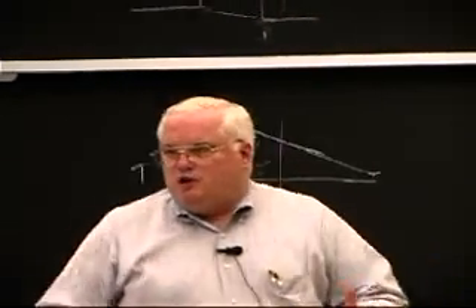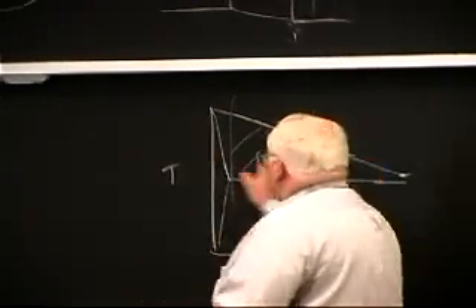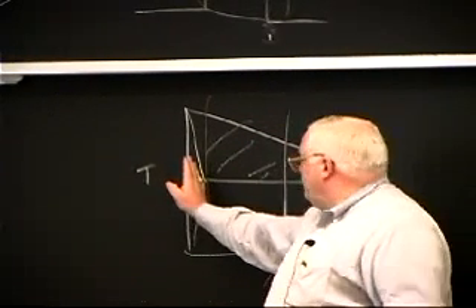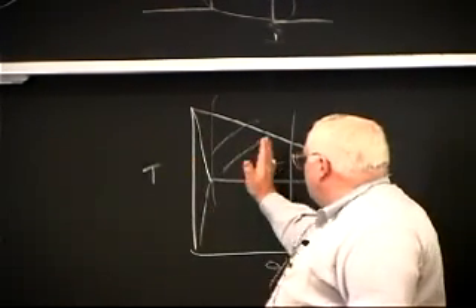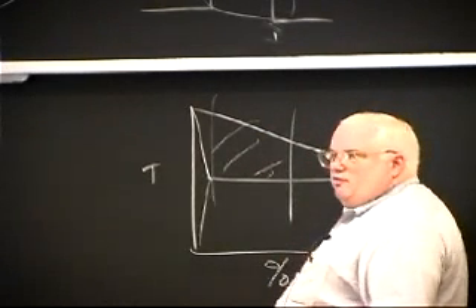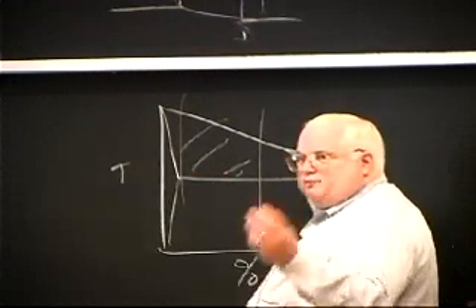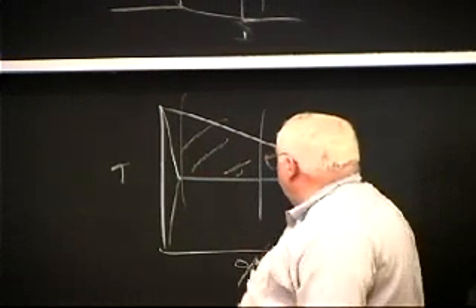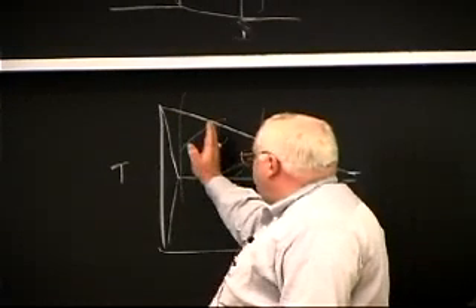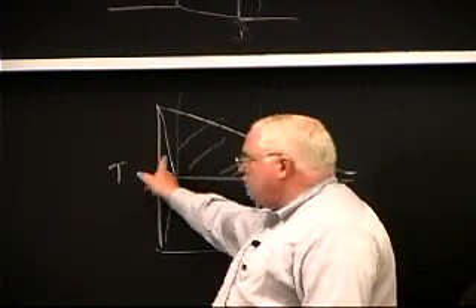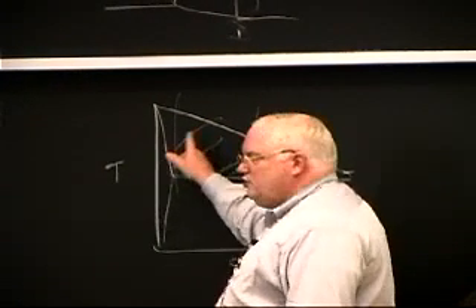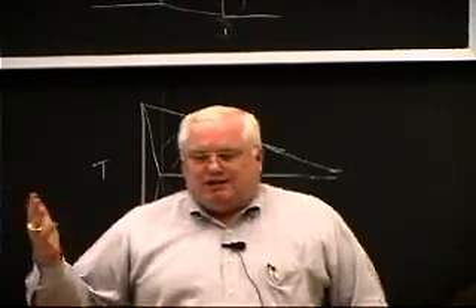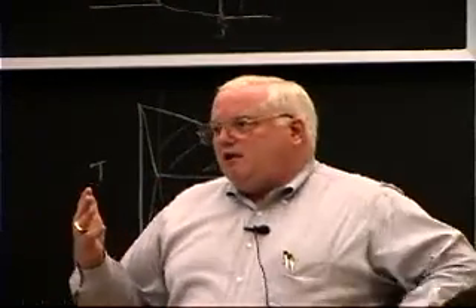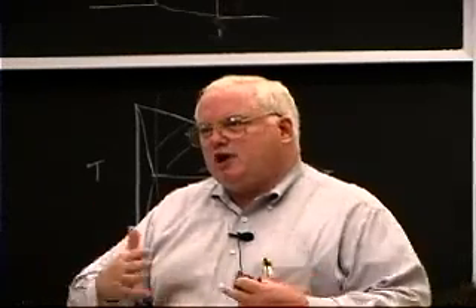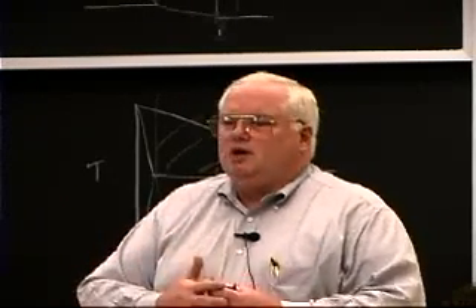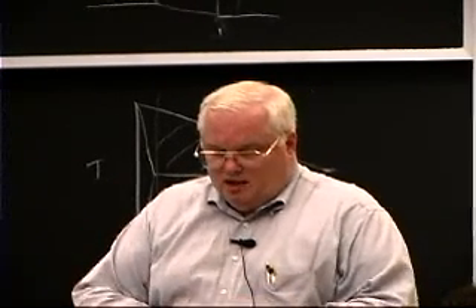In aluminum, we can either adjust to be very rich or very lean in the alloy composition. In the nickel alloys, well, you don't want to go very rich because you're trying to get high temperature out of a lot of these alloys, like for a turbine blade. So you can't go over here. You have to have enough to give it enough strength. If you're too lean, you can't get enough high temperature strength. So you actually end up in this region to get the high temperature strength. And you try to weld it, you have this big solidification range, big thermal stresses because of the big delta T, and you get cracks.